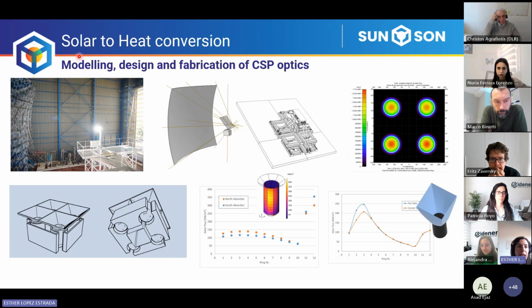So regarding the solar to heat conversion part, the idea is to use a solar furnace, which is located in the Plataforma Solar de Almería. So the idea is that the sunlight comes from this aperture and reaches this first mirror, which is a parabolic mirror. And this mirror focuses the light on a secondary mirror that has a butterfly shape, as you can see here. This is more in detail.